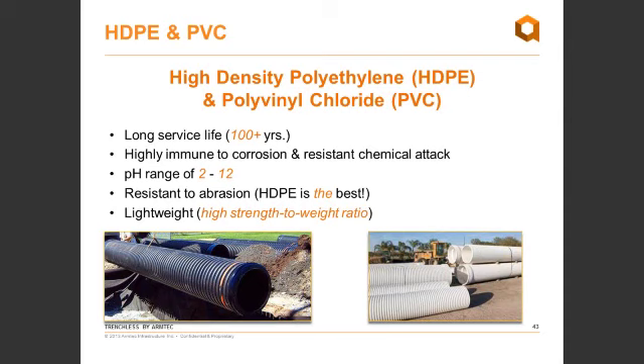So these plastic pipes are also very resistant to abrasion, and this is one thing that we like to highlight, particularly with HDPE pipe, because HDPE is actually the best pipe material in terms of abrasion. This has been tested and it actually comes out on top, better than PVC, significantly better than steel and concrete pipe. So it might be little known, but definitely a good pipe to use in abrasive conditions. And another thing to note, when you consider a coated steel pipe, if it's abraded, you're going to lose your coating. Whereas if you do lose some wall thickness on a HDPE or PVC pipe, underneath it's just more HDPE or PVC. It's just more plastic.